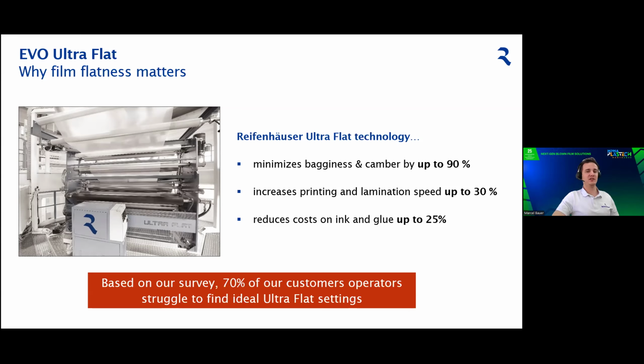So you stretch a bit, not really stretching, it's like a draw, for 1, 2, 3%. And then you first heat up a bit, like an iron, and then put some tension on it to get out the wrinkles, bagginess, and camber. And then you cool down to freeze the setting.